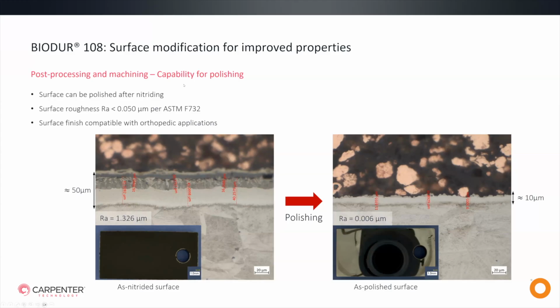So, we've done extensive testing, including some of the ASTM F732 wear evaluations and fatigue assessments that show that cold worked BioDur 108 and nitriding maintains that mechanical integrity while delivering greater than 50% wear reduction compared to some of the alternatives. And again, I would encourage you to check this out in the patent. So in short, when it's applied properly, when it's applied correctly, nitriding enhances surface performance without undermining the base material's capability for toughness and performance.